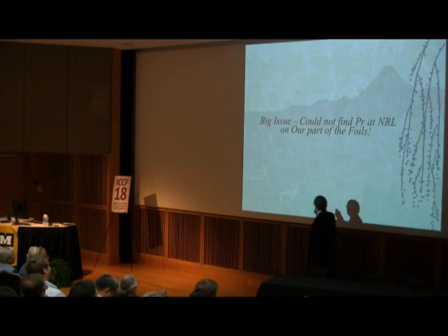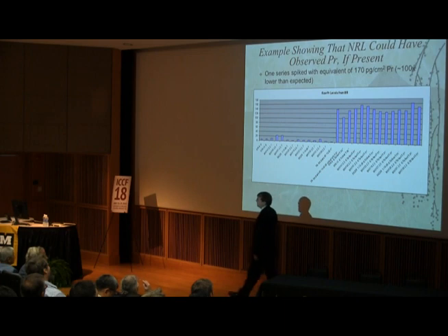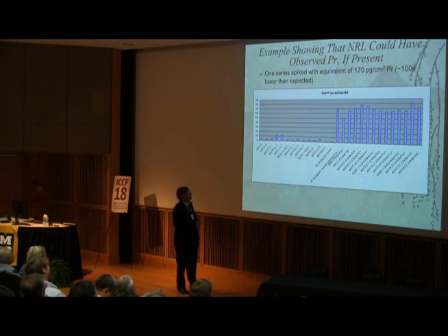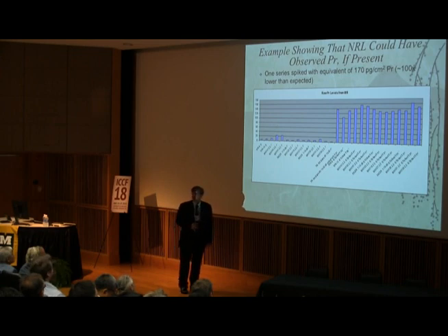Maybe it had diffused into the surface of the foil. We developed a procedure where we could look at the impurities in the palladium down to parts per quadrillion levels. So here's a spiked sample, 1,000 times lower concentration, 100 times lower than was found in those extracts. Here are the spikes, here are the samples, and you can see that we would have seen it if it were present.